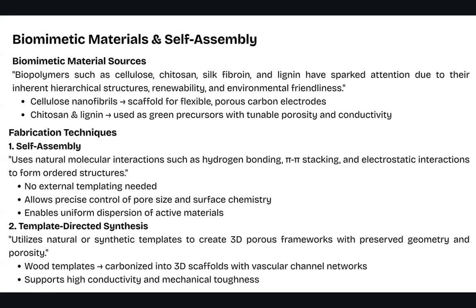The second is template-directed synthesis. It utilizes natural or synthetic templates to create 3D porous frameworks with preserved geometry and porosity. An example of this is wood templates, which can be carbonized into 3D scaffolds with vascular channel networks. It supports high conductivity and mechanical toughness.